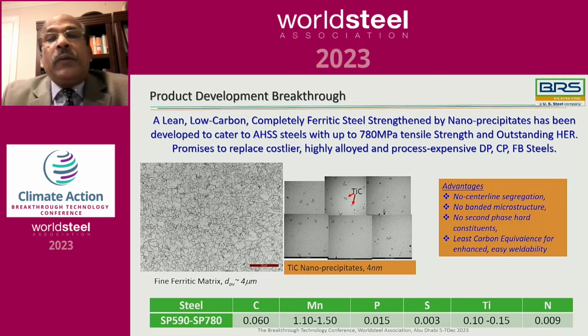So at Big River Steel, we have developed a very lean, low carbon, and completely ferritic steel that is strengthened by nanoprecipitates of microalloyed carbides, and it comes with a tensile strength of 780 MPa and outstanding HER. You can see the microstructure is totally ferritic, 100% ferritic, and the strength is derived by the titanium carbide nanoprecipitates, about 3 to 4 nanometers in size within the grain.